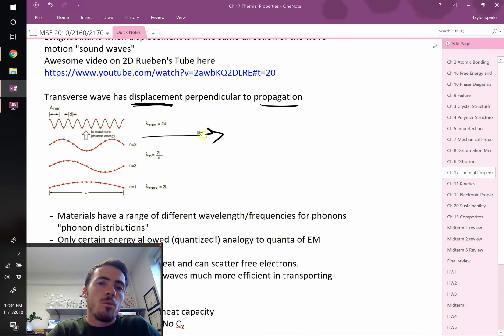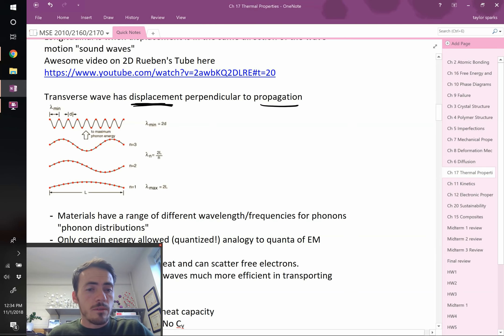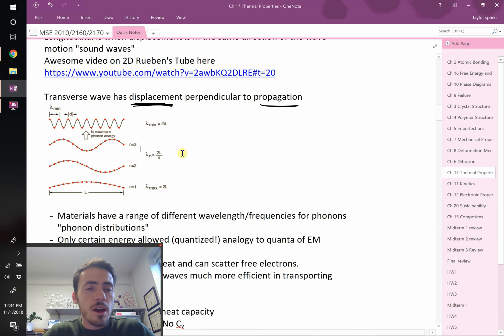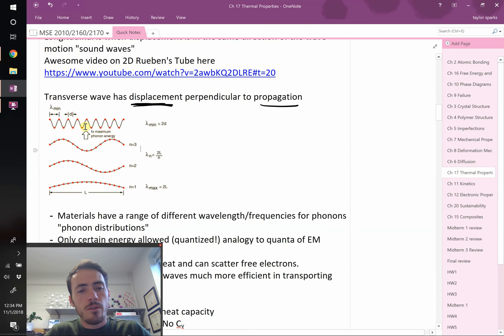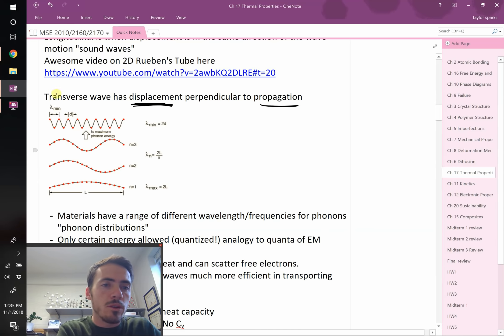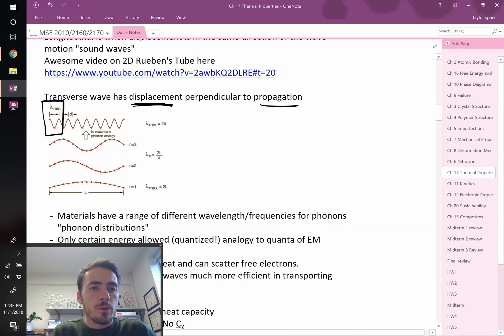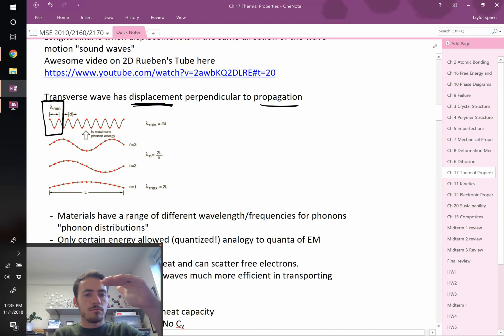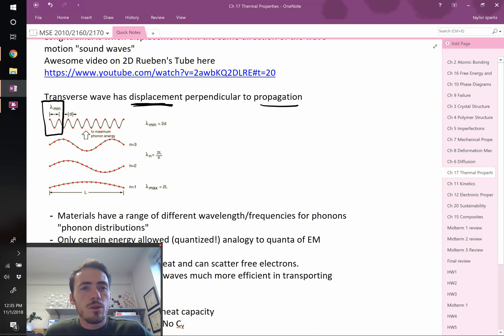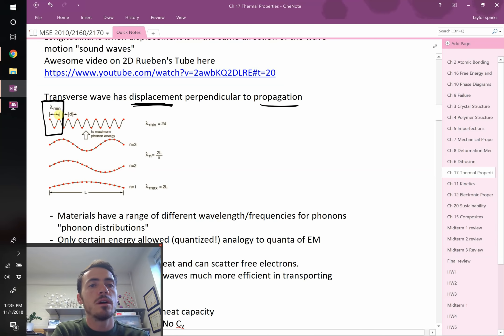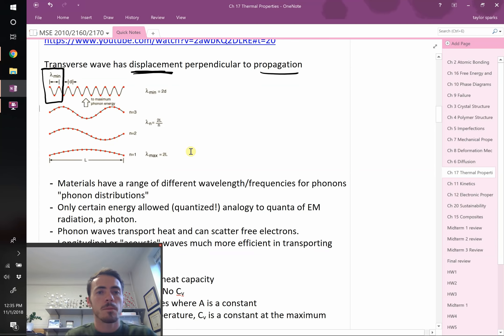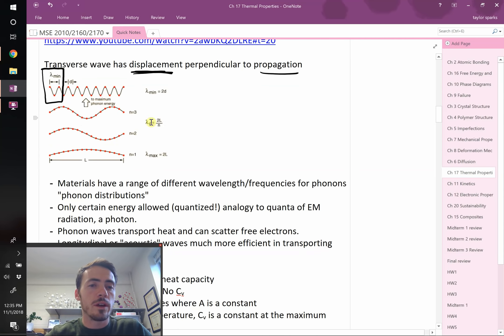When it comes to phonons — which are waves of displaced atoms — there's a fundamental limit to how small the wavelength can be. You can't have an arbitrarily small wavelength, because the wavelength is made up of atoms themselves. The smallest wavelength you can get is crest-trough-crest across three atoms. Because atoms have a minimum bonding distance, that puts a lower limit on how small these waves can be. However, they can be very large, so there are lots of possible wavelengths.